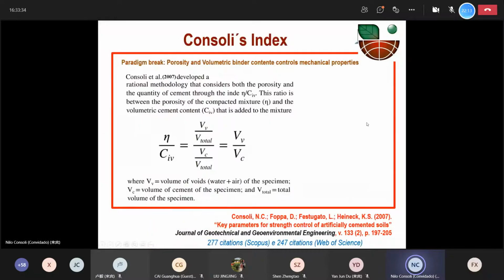But the title of this presentation was like, after so many years of research, we have not had until that moment, and so I call back to 2007, a way of dosing, let's say, the amount of any kind of cement that in our case is not just to insert some kind of binder, but also you have the compaction. So you realize that differently from concrete, for example, in our case, we can control the porosity of the material through compaction. And here we create a new variable, which is the volumetric cement content.